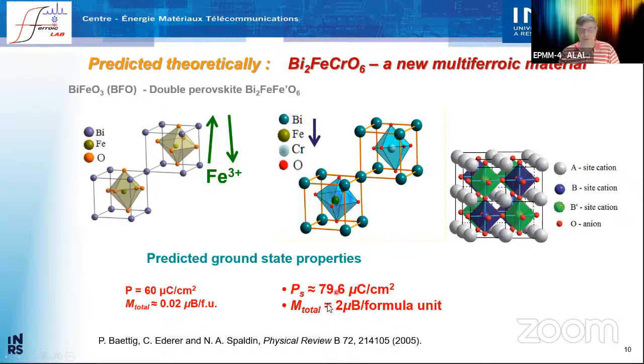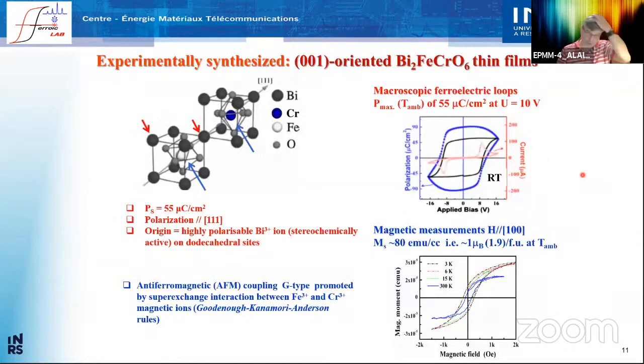Like you see, it could become a material with 2 Bohr magnetons per formula unit and also very good properties. The only thing is that in order to do that, you have to have a cationic ordering. You have to have, along all the directions, an ordering of chromium and iron and chromium and iron. And people didn't really know how this would happen, and if it would happen, it has been controversial for a long time, until actually we decided just to try. And we did find some conditions in which this cationic ordering is actually happening.